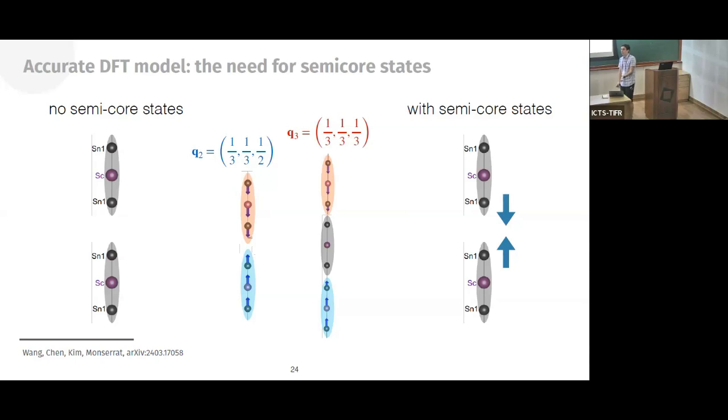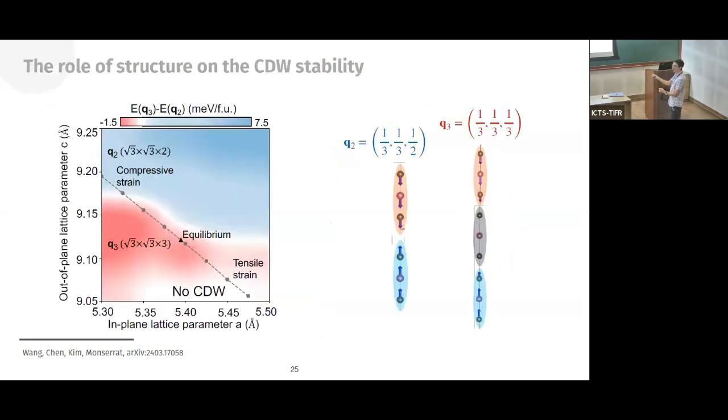Okay, so are you using some kind of norm-conserving pseudopotential or ultrasoft? Yes, so we tried both, and we actually also cross-checked with all-electron calculations. So we've done a lot more than what I'm showing here. So basically, the type of pseudopotential doesn't matter? No. But again, you can find slight differences perhaps with the functional that you choose and so on, so this is always tricky to say. But we've tried many different things. That was just to illustrate the point that DFT calculations can be tricky and you can get any answer you want. But what I want you to take home from this is that it's the C lattice parameter that dominates that, and as long as you're in the right regime, then you can get the right physics. Yeah, thanks.